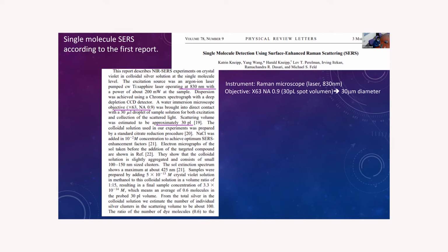So they are only measuring in a very small volume, so that could be the clue of this measurement. To continue, the scatterer and the enhancer of the signal will be a colloidal silver solution. They don't say the concentration, but usually this kind of colloid has a concentration of about these values. That means that in this volume, we will have between 100 and 1,000 nanoparticles.